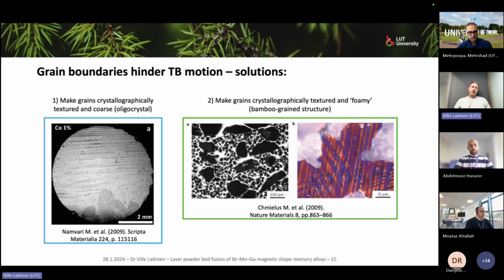The other way is that we can make these grains crystallographically textured, but have the material itself be very foamy. This is a structure with tiny single crystals which form an interlinked structure, and this is what we call a bamboo grain structure. And this can also actuate. It's like a metallic foam. Usually we use an approach which combines the best parts of both, so we get the force output of the left, but the design freedom of the right side.